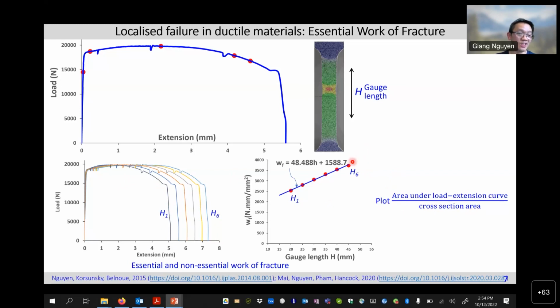So this is not my invention. It has been there in the community of ductile fracture for 20-30 years. And if I plot this, I get a unique thing. There's an equation behind that I wouldn't show here. So the line here, the slope, is the non-essential work of fracture. The work that is dissipated under plastic deformation only. Okay, the intersection with the vertical axis here is the essential work of fracture. That means the work that is dissipated when we create fracture at this location.